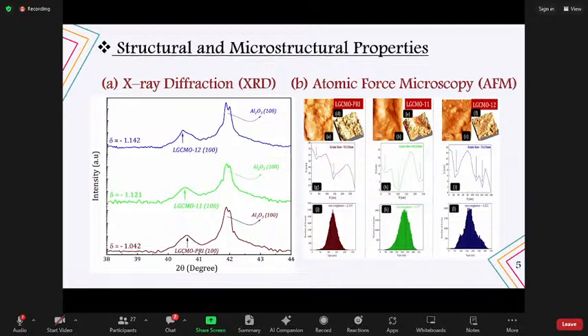The figure at the left-hand side shows the structural property obtained by X-ray diffraction. From the graph, we can see that all the films possess a single-phasic nature without any detectable impurity within the measurement range employed. There is a visible separation between the XRD peaks of film and substrate in the 42° 2θ range. To know the lattice mismatch between the film and substrate, it can be calculated using the strain formula, that is d film minus d substrate divided by d substrate.